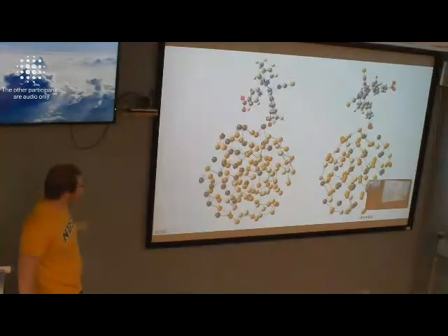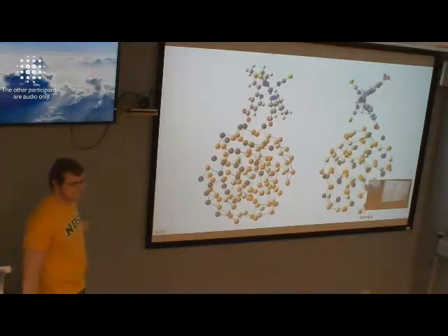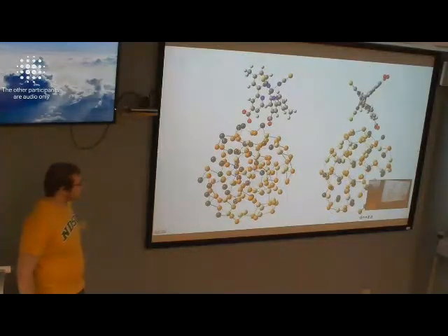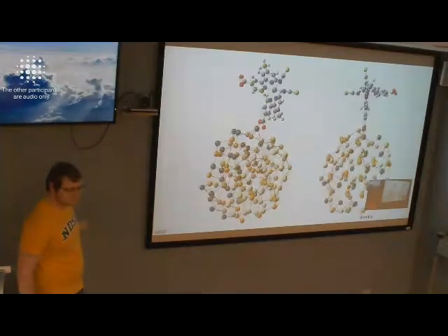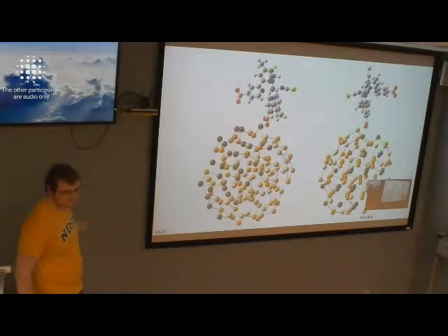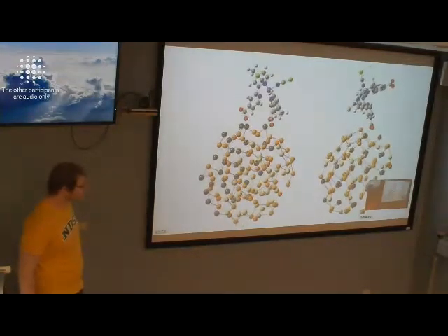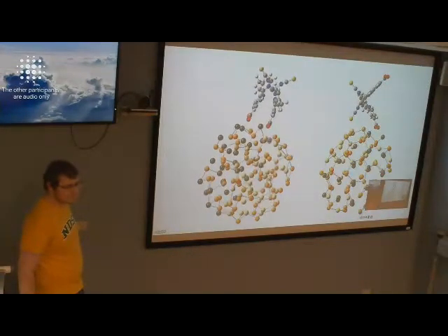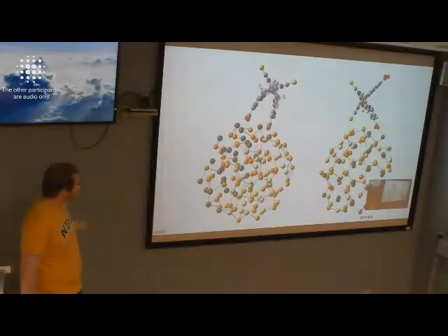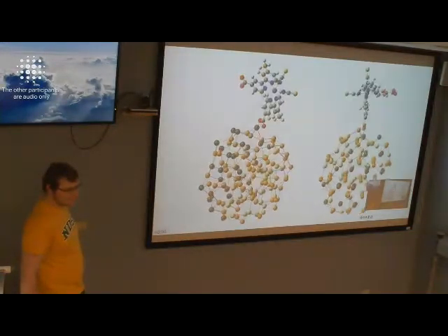And this rotation and reorientation probably really helps to minimize the overall total dipole moment, when both the dipole of the surface at the interface and the total dipole coming through the molecule should kind of compensate each other and hopefully provide the least possible dipole in the final structure. And this probably dictates this reorientation of molecules, that they want to go with both to the surface, right? Because when another one is going up, you are probably not compensating completely the dipole at the surface, since the dipole of the molecule is not as big if you reorient it this way.